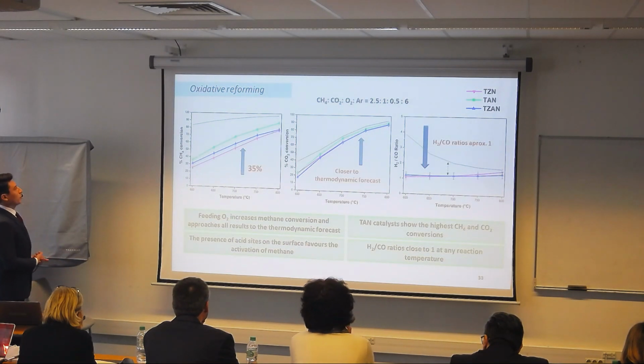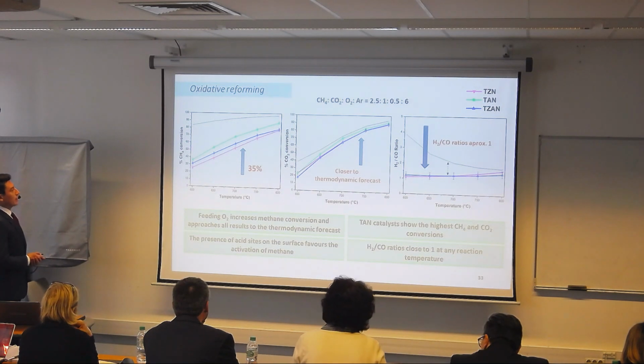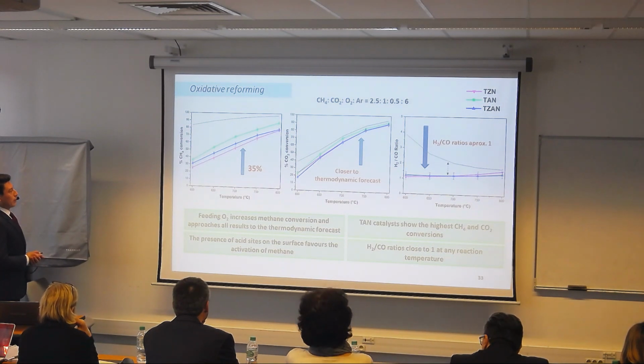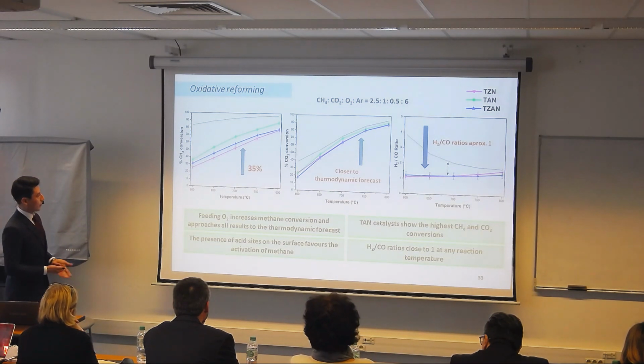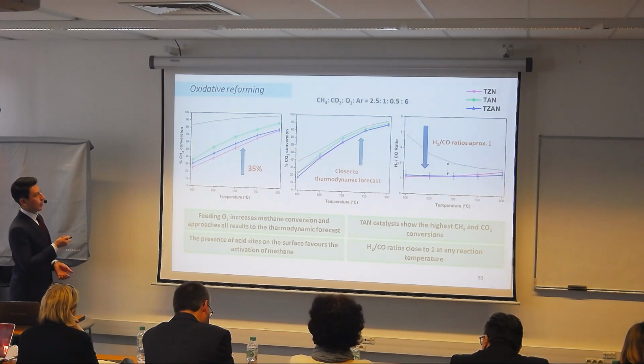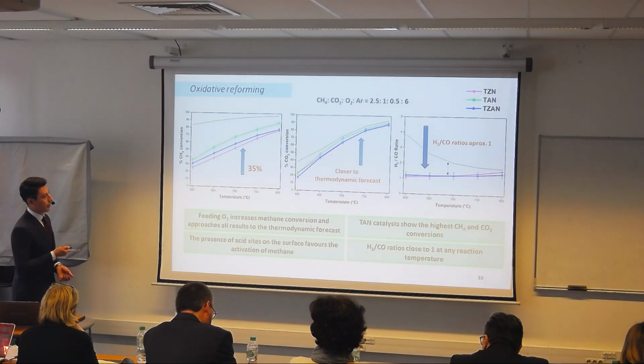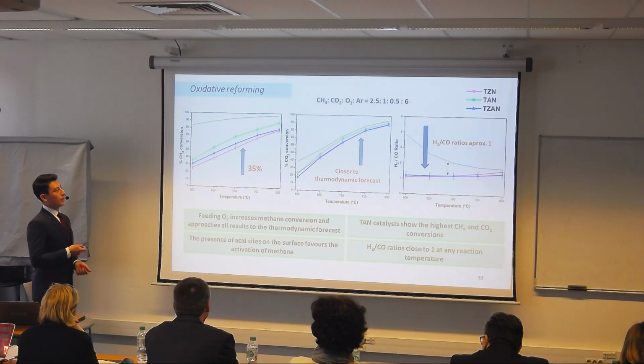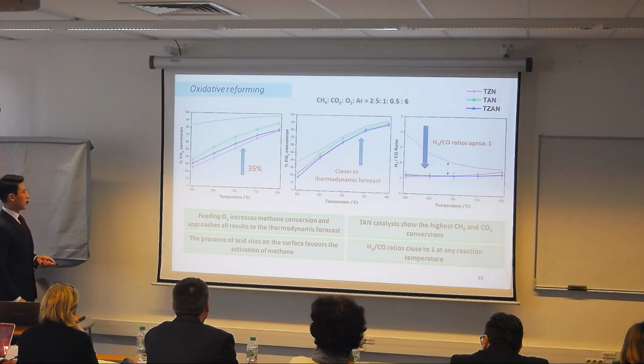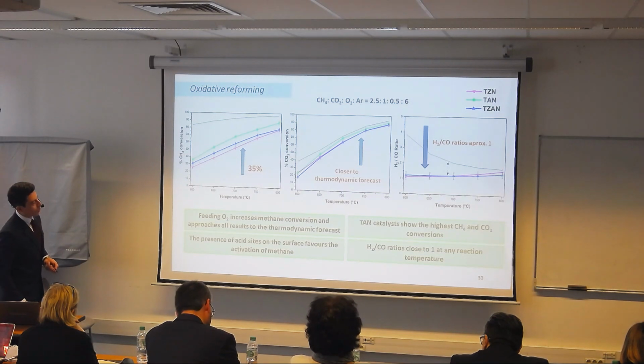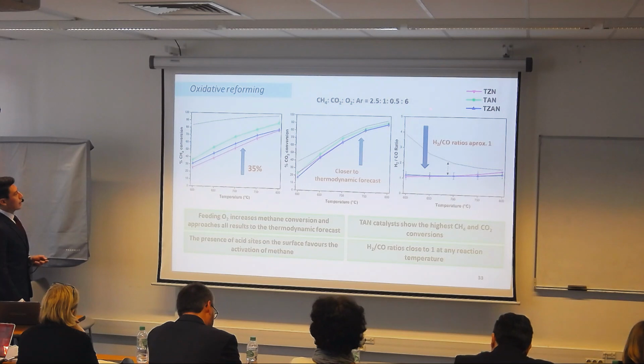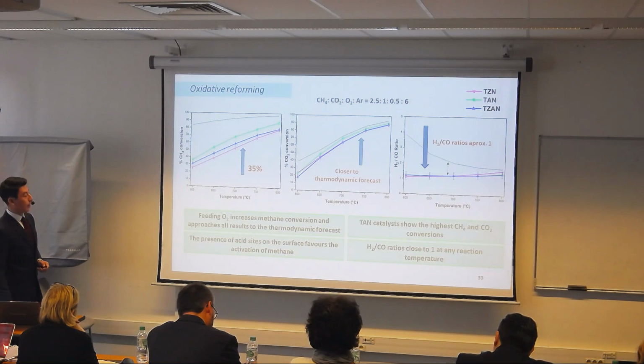We moved to the oxidative reforming, and we can see a very clear effect of the oxygen. We increase the conversion by around 35%. For CO2 we are getting closer to the ideal equilibrium, and all the values are approximately 1. So feeding oxygen increases the methane conversion and approaches the results to the equilibrium. The best catalyst was the one with titanium, alumina and nickel.